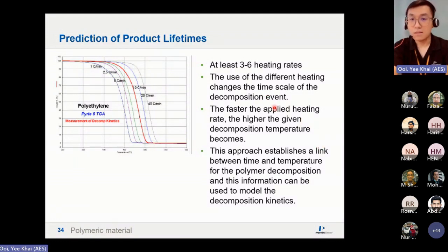Of course, the faster you heat up your material, the higher the decomposition temperature becomes. This is what we call the thermal lag effect. Why is this so? Because in order for a material to decompose, each part of the material must reach the same temperature. If you heat up very fast, your sample cannot catch up with what you're programming. It takes time for the whole material to reach the same temperature. So at 1 degree C, because you heat slowly, your material can catch up, so there is reduced thermal lag and it decomposes at this temperature. But at 40, it pushes from here all the way to here, because it takes this long for your material to reach equilibrium for the decomposition temperature.